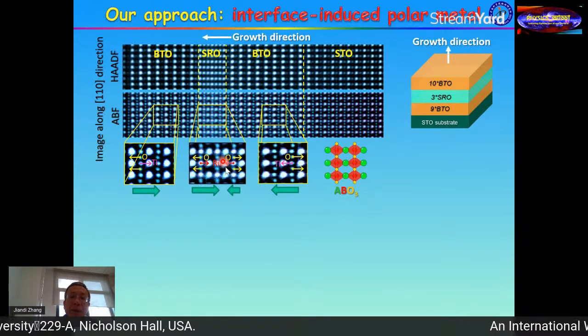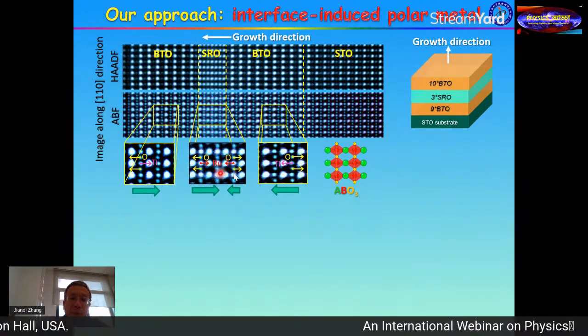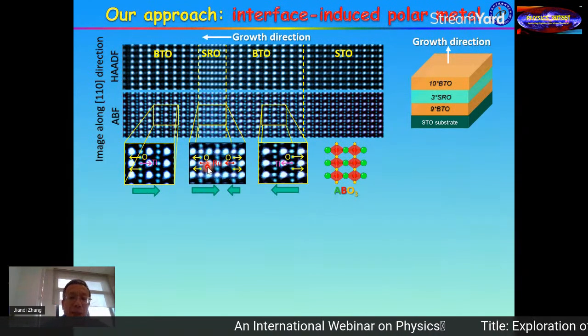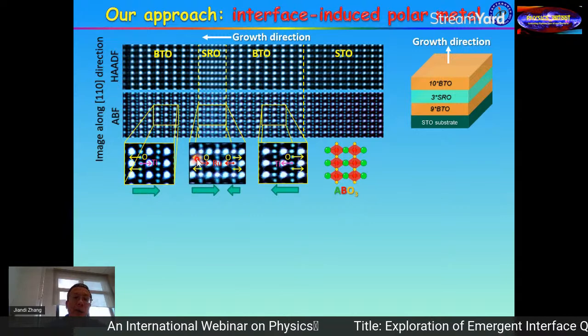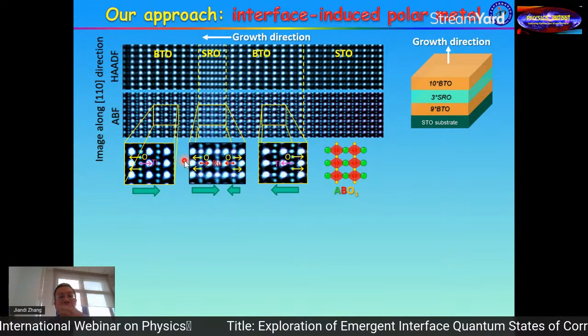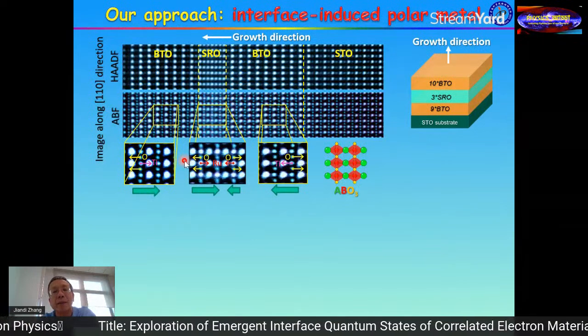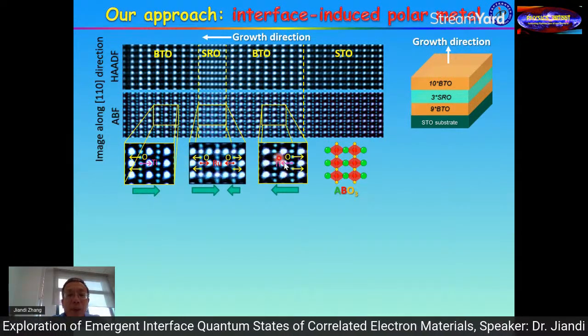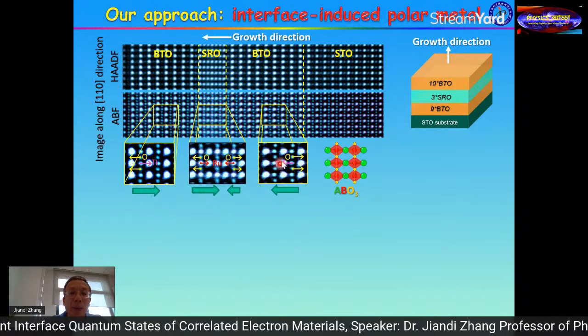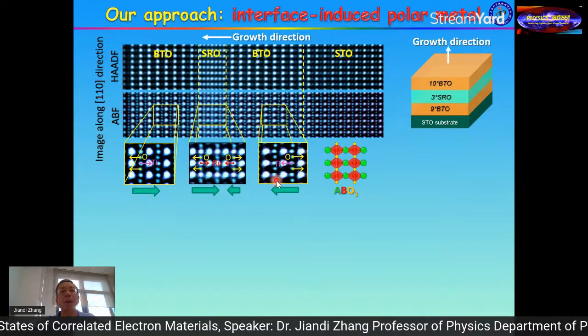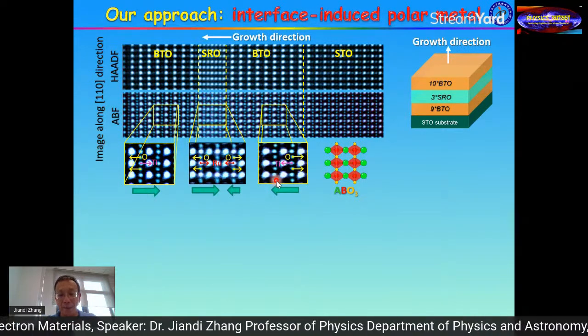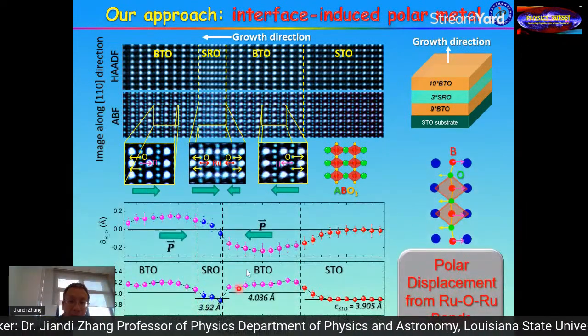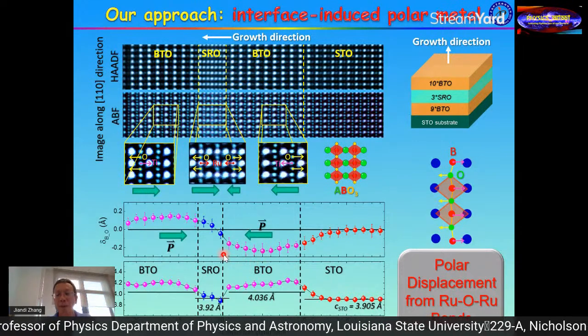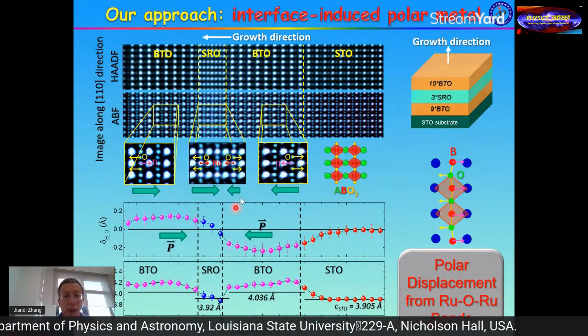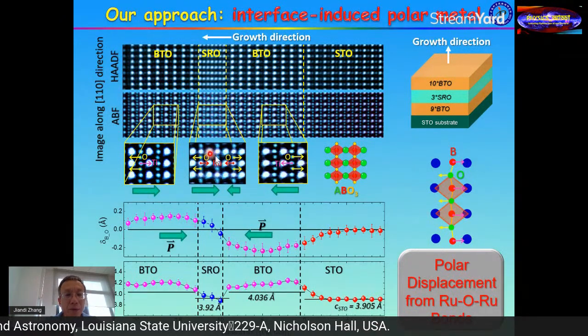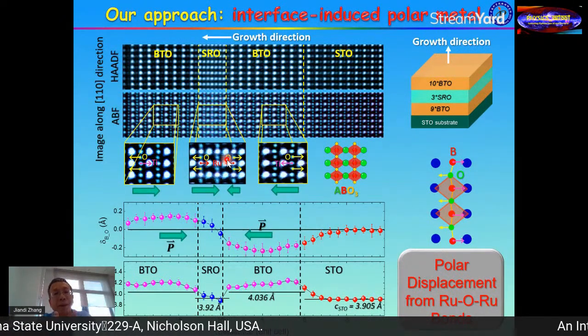So we found out that in the strontium ruthenate, they do have a polar character, because the ruthenium atom is moving in one direction while the oxygen moves in the other. And that creates an internal dipole moment. And this follows because the barium titanate has a similar kind of moment or displacement of the atoms. Okay, so you can find out the detailed displacement of those atoms. So suppose I create this kind of polar displacement in this very thin strontium ruthenate layer.